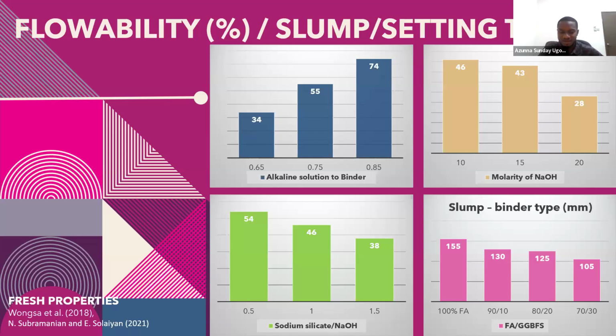So if the purpose of your concrete is a concrete that requires a high workability, you have to reduce the quantity of sodium silicate in the mix. That is the summary of what this means. Then another factor that affects the workability, like I said, is the calcium content, the calcium oxide in the binder. So if you look at the third part, where I indicated the slump and the binder type. So if you see the first chart there is about 155 mm, which is the highest slump. That one is 100% fly ash. There's no GGBS in it.